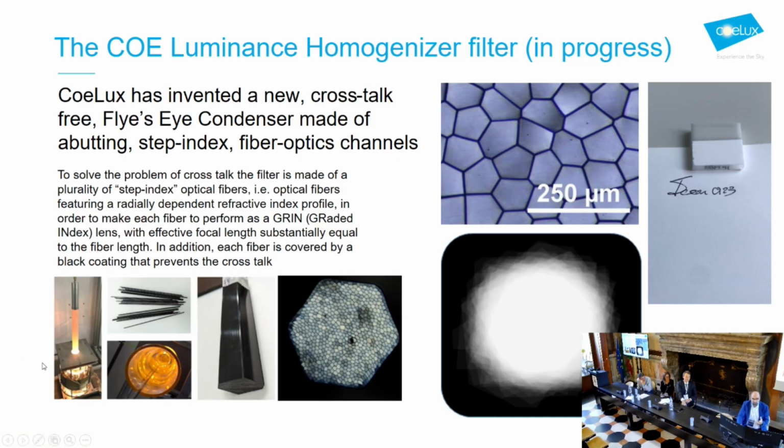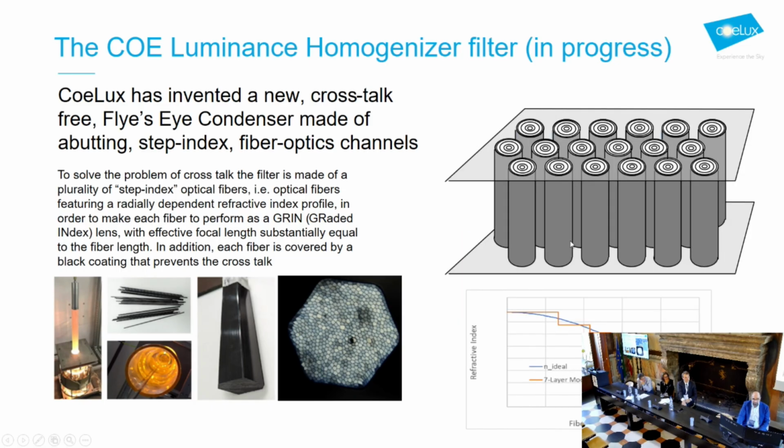How are they made? You start from a cylinder, a polymer cylinder here. You create this spaghetti, so the fiber which is drawn. You cut them, then you glue them together in a single block, and then this block is again put into the oven several times until in every spaghetto there is inside this large number of fibers, so that you are creating this at the end.